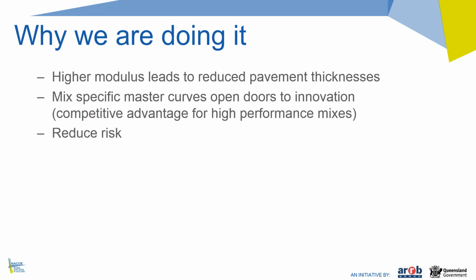So that brings us to why we're doing it. These higher moduli lead to reduced pavement thicknesses, especially in climates like Queensland. The mix-specific master curves open doors to innovation. So instead of assuming a relationship between temperature and modulus, we can now actually test it, and that means that people can optimize their mixes to get a better outcome.